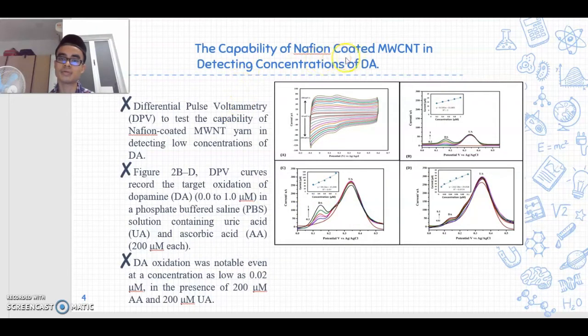Next, I would like to present the capability of Nafion-coated multi-wall carbon nanotube yarn in detecting concentrations of dopamine. For further investigation, differential pulse voltammetry was used to test the capability of Nafion-coated multi-wall carbon nanotube yarn in detecting low concentrations of dopamine. Figure 2B to 2D showed the differential pulse voltammetry curves recording the target oxidation of dopamine from 0 to 1 micromolar in a phosphate buffered saline solution containing uric acid and ascorbic acid at 200 micromolar each. Dopamine oxidation was notable even at a concentration as low as 0.02 micromolar in the presence of 200 micromolar ascorbic acid and 200 micromolar uric acid.